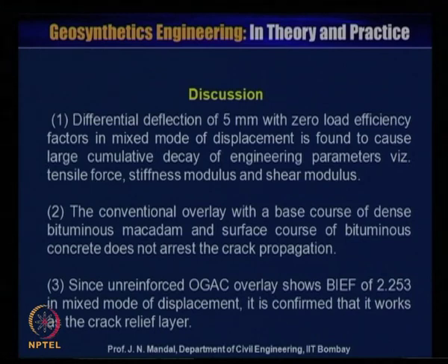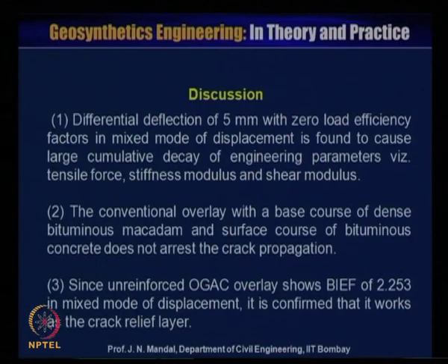So from this, what we can discuss: one, the differential deflection of 5 millimeter with zero load efficiency factor in mixed mode of displacement is found to cause large cumulative decay of engineering parameters, that is tensile force, stiffness modulus and shear modulus. Second, the conventional overlay with the base course of dense bituminous macadam and surface course of bituminous concrete does not arrest the crack propagation. Three, since the unreinforced OGAC overlay shows a BIEF of 2.253 in mixed mode of displacement, it is confirmed that it works as a crack relief layer.